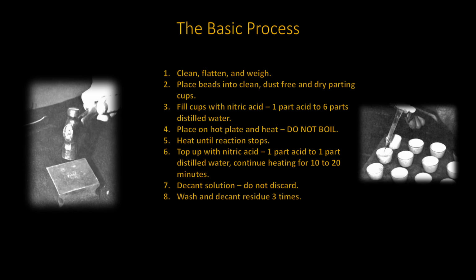Wash and decant the cups at least 3 times, removing as much water as possible without loss of residue. When washing, ensure that the water stream is a fine stream. When adding the water, pour it down the sides of the cups to avoid direct stream contact with the bead or fine gold powder. You do not want to impact the bead. This may cause it to break apart.